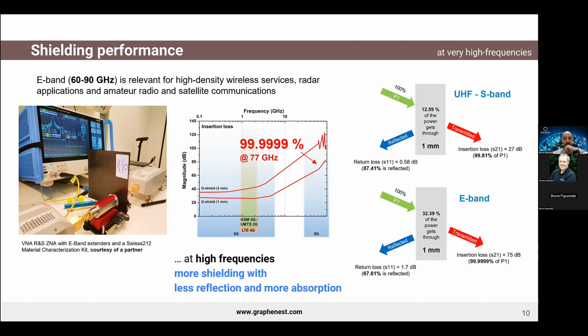So at the UHF S-band, only 12% of an incident power is allowed to penetrate the shield. So roughly 87% is reflected. While at the E-band, this value is roughly 32. So much less power is reflected at high frequencies. However, as you can see, from that 32 that tries to penetrate the shield, only 0.0001, which is 100 minus 99.9999%, is allowed to be transmitted through it. So at the end, at high frequencies, we have more shielding because we have less reflection and more absorption.